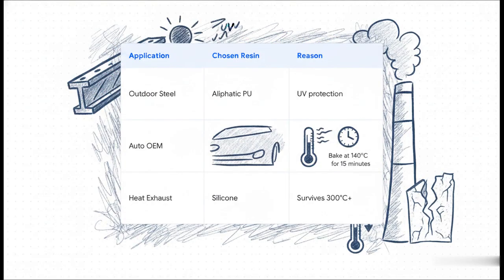And this brilliantly illustrates how the real magic happens out in the field. Senior engineers don't just pick one resin off a shelf, they architect complete systems. Got heavy-duty outdoor steel? You're laying down epoxy for that 15 MPa grip, and then topping it with aliphatic PU to shield it from the UV rays. Automotive OEM? You pair acrylic and amino, bake it at 140 degrees for 15 minutes, and hit a stunning 90+ gloss. Extreme heat exhaust stacks? You deploy silicone, surviving past 300 degrees where any carbon-based paint would literally vaporize into ash.